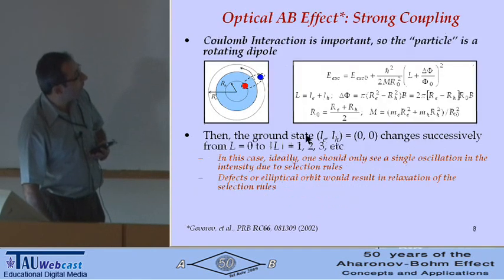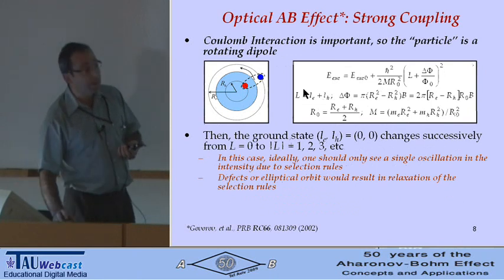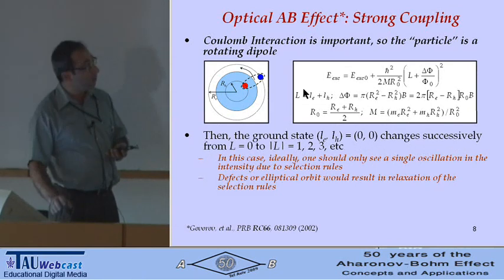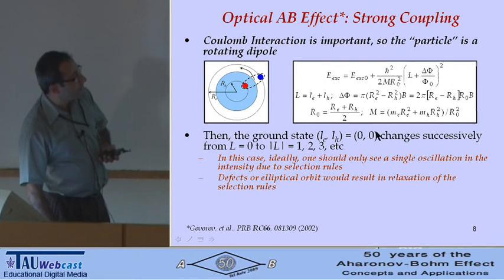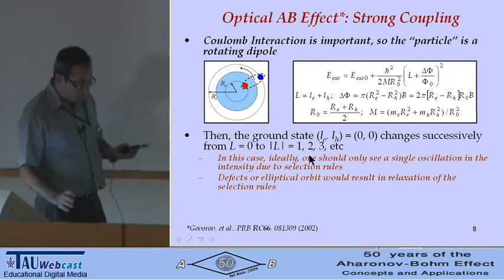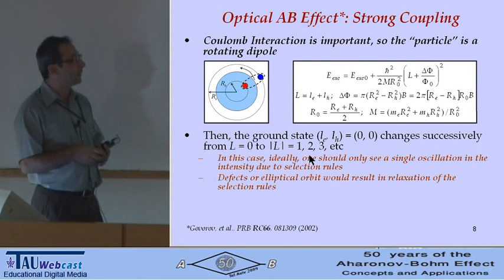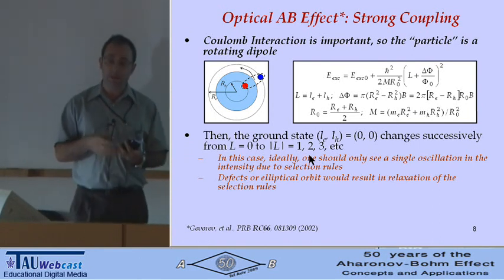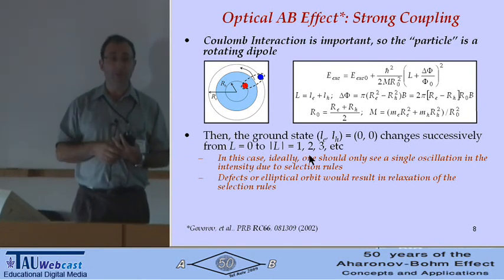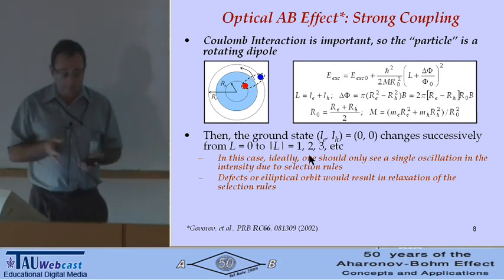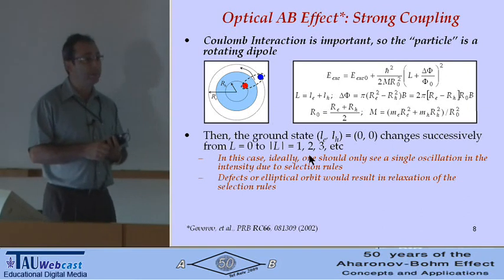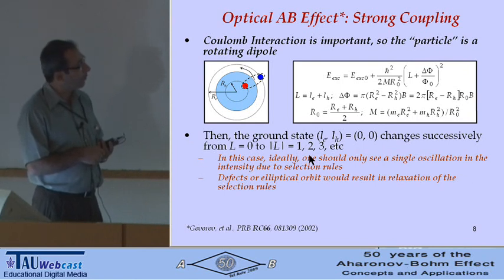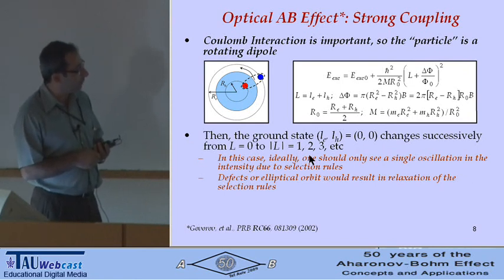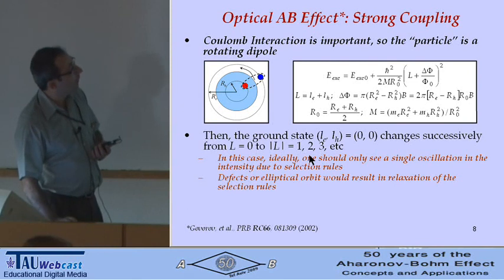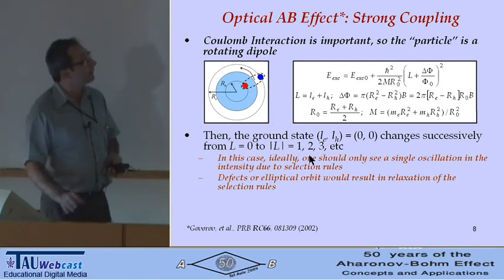And of course, in the second case, when the Coulomb interaction is important, you have to consider the exciton as a total, and then you have to work with the total orbital momentum. And here it is a little bit less interesting in a sense, because you expect only one oscillation. But of course, in real life, it doesn't happen. We have more oscillations because you have defects, and you have not perfect symmetry, and you have coupling of different orbital momentum and relaxation of the selection rule. So that's the introduction and theory. Let's see if we can see it experimentally.